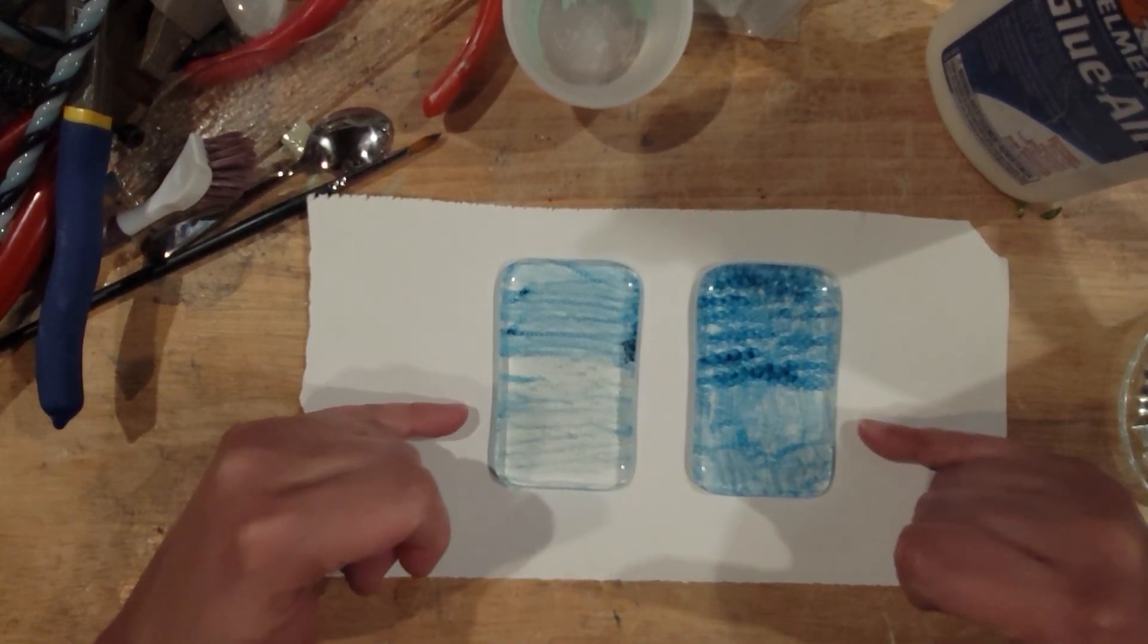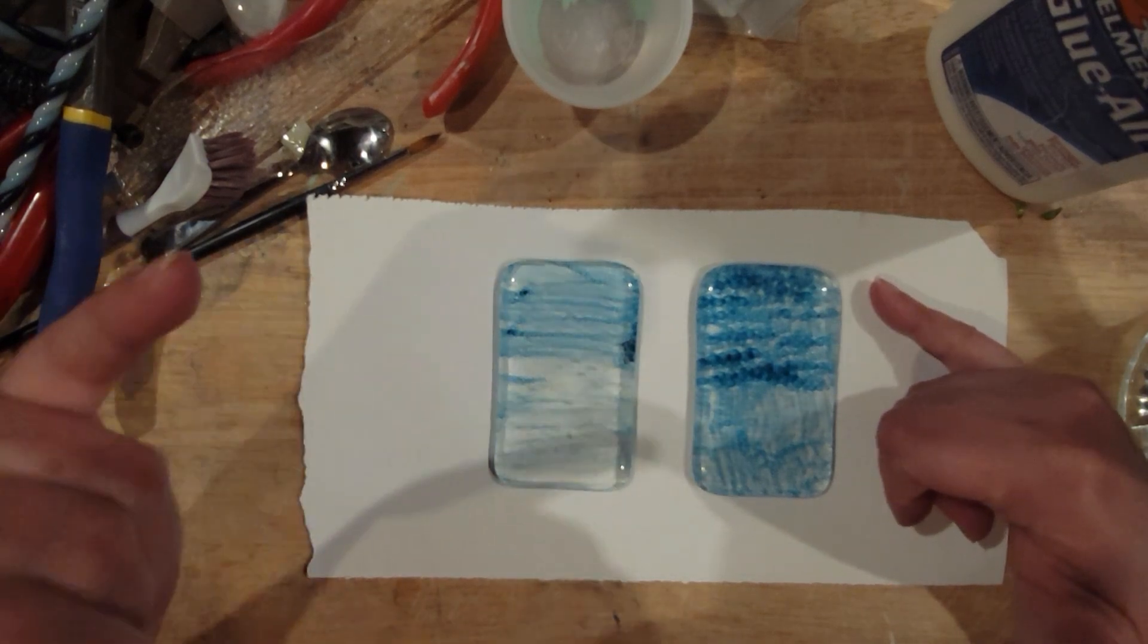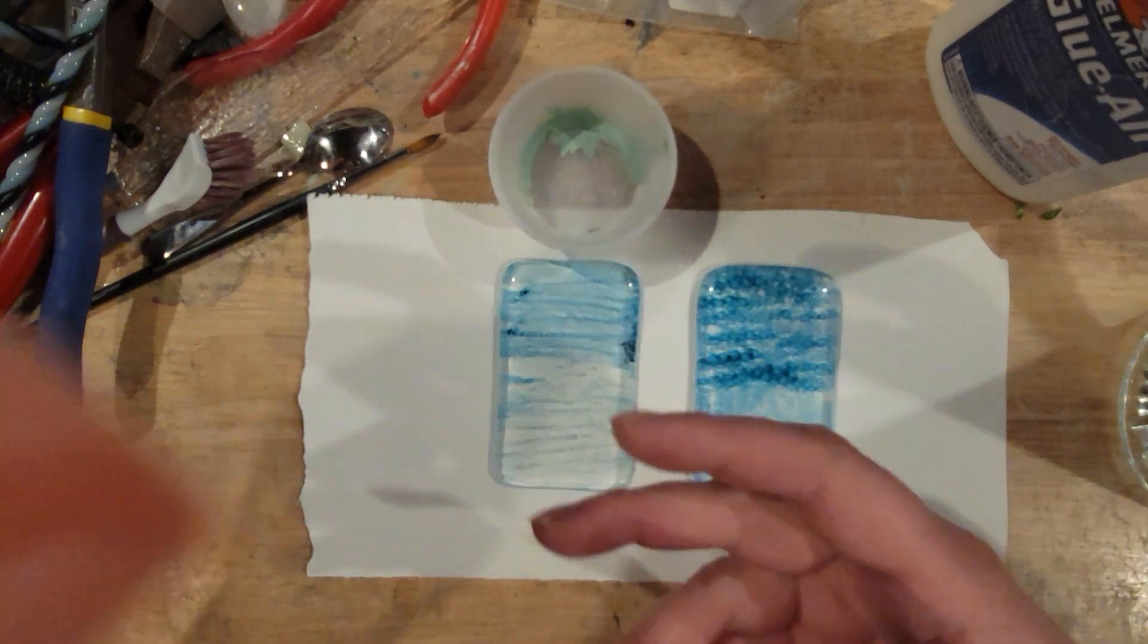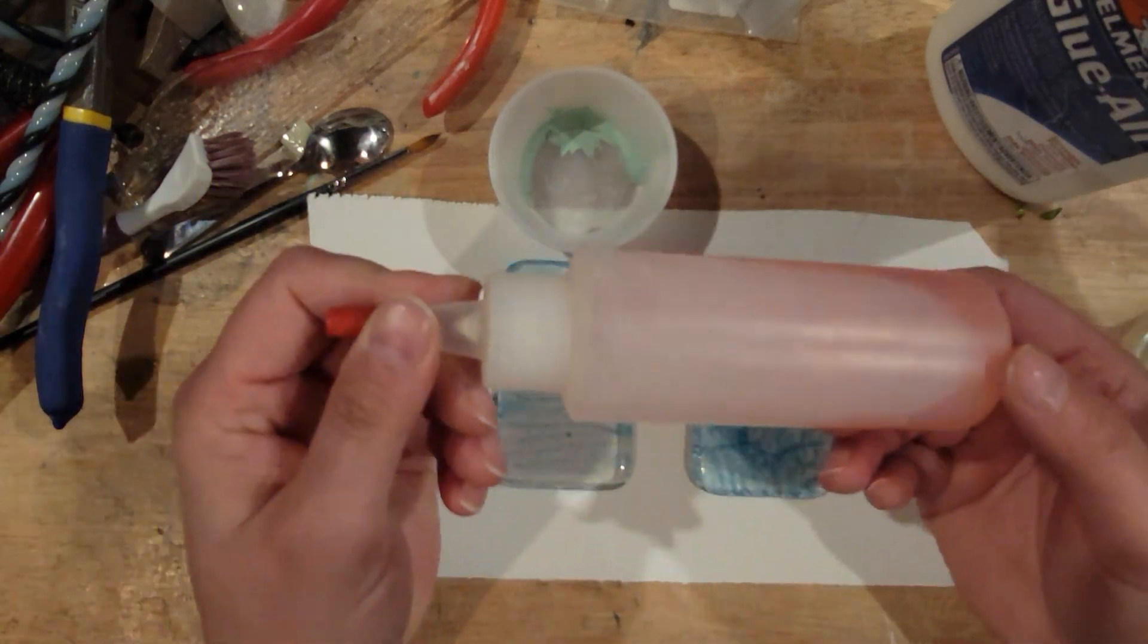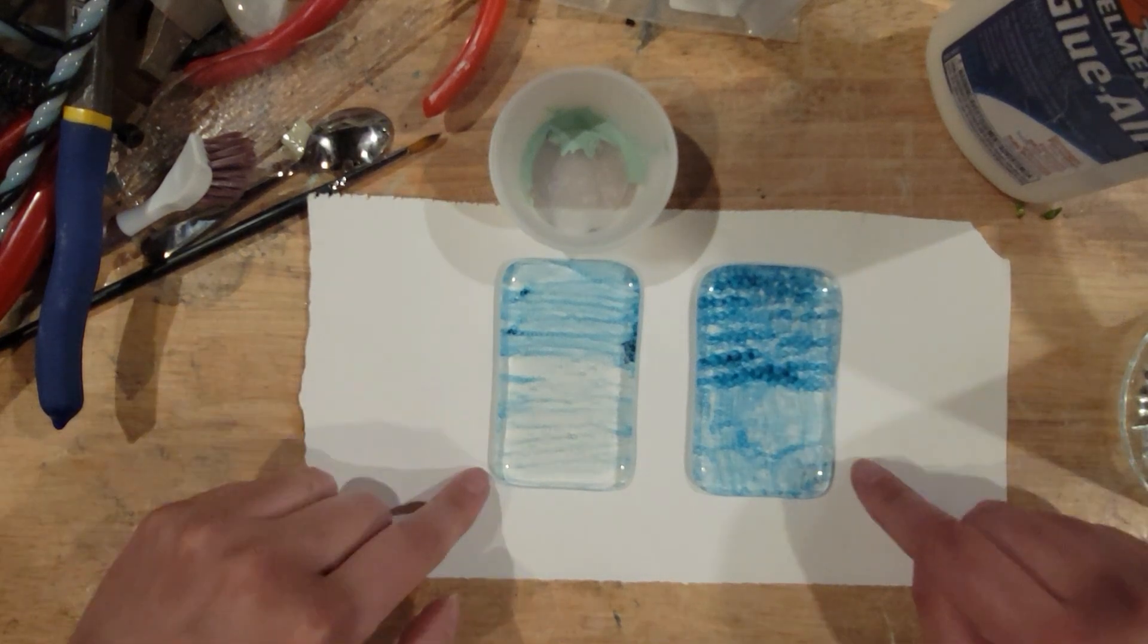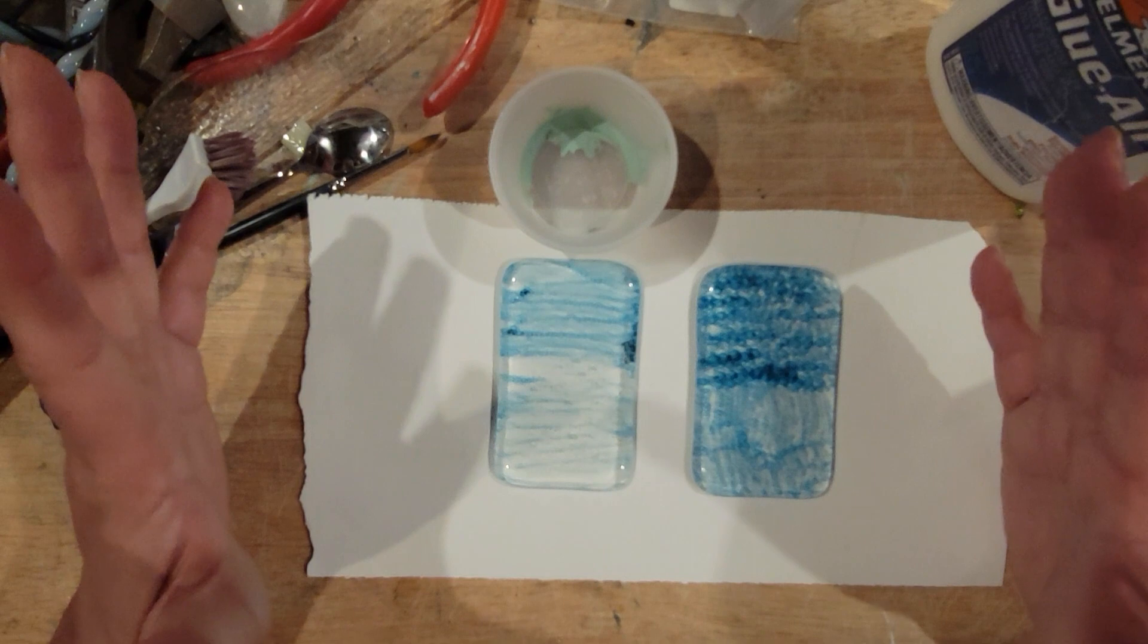But this was an interesting little test of two essentially identical pieces. Again, these pieces were two millimeters on the bottom, a layer of copper carbonate or oxide mixed with original glass tack, the red thin stuff, painted on thick on the top, then on the bottom, topped with two layers of two millimeter and then full fused.